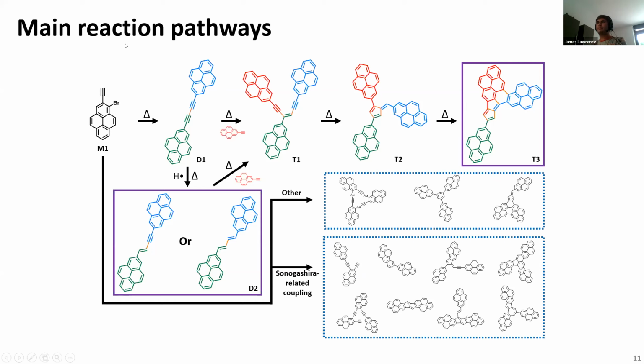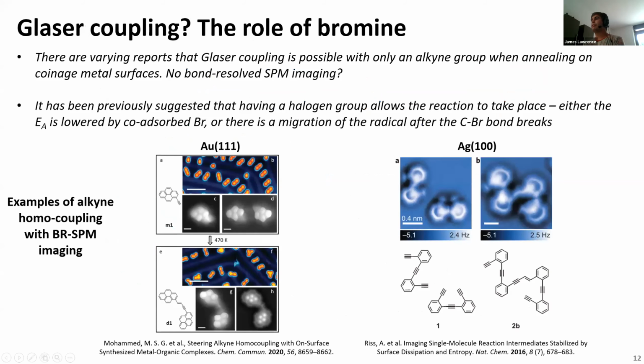Now, if we instead just focus, as an aside, on the formation of this Glaser coupled dimer, this straight dimer here, there's some potential controversy about what you actually need to form this dimer. In particular, what is the role of this bromine here? So in the literature, there are several reports of molecules with alkyne groups adsorbed on, for example, gold or silver surfaces, heated up, and the claim is that they form this Glaser coupling with a straight linkage between the alkyne groups.